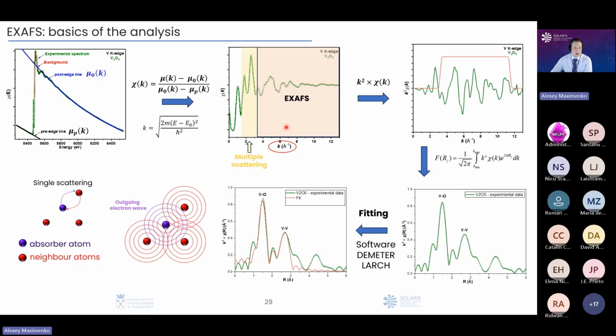Now let's come back to the EXAFS region of our X-ray absorption spectroscopy absorption spectra. As I told you, in this range we mostly speak about the single scattering path of the photoelectron. Here you have this photoelectron going from our absorbing atom, scattered and coming back to our absorbing atom. And these features are hidden somewhere here. In order to work with them, we need to somehow get them from our main spectrum. In order to do this, we get rid of this background.